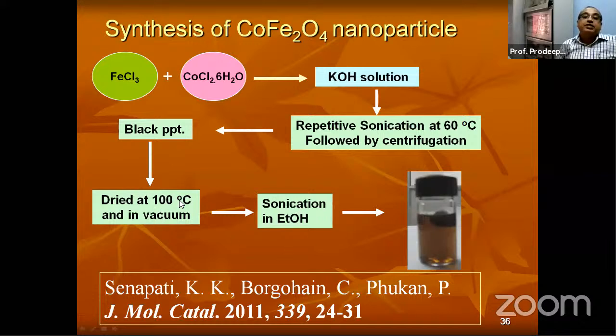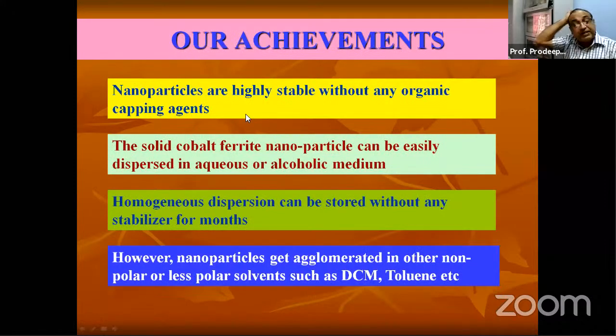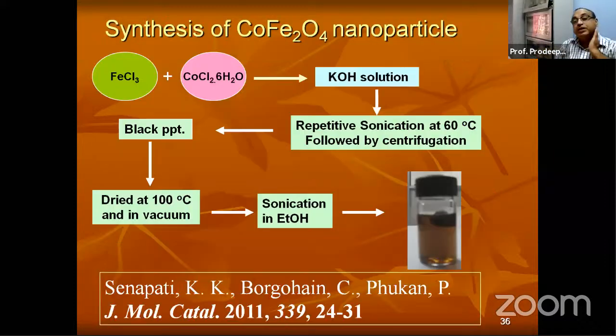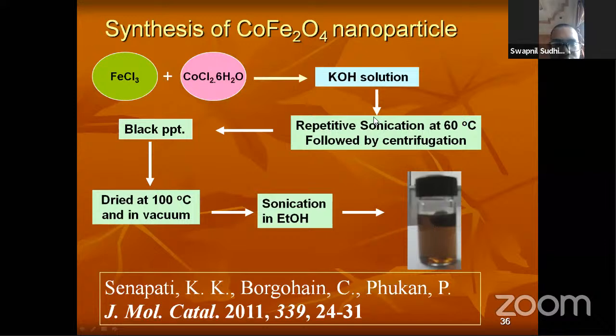Then we got the black precipitate, then dried at 100 degrees. After drying this, we took it in ethanol, then repeatedly we sonicated to get this particular, it's a kind of almost transparent colloidal solution. Okay, so like this we made these nanoparticles. Then what is the advantage? You can see here what we achieved actually. Of course, it is 2011, and till then nobody had used the sonication method for synthesis of such nanoparticles.